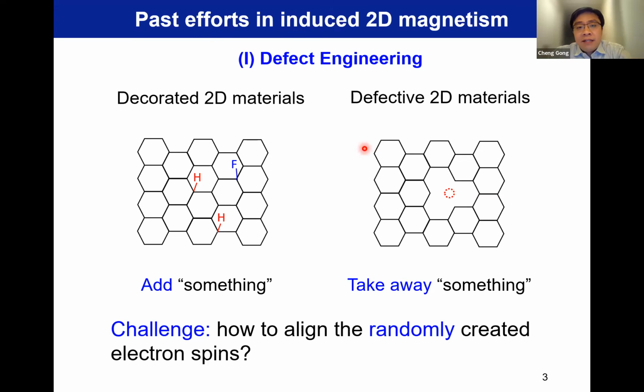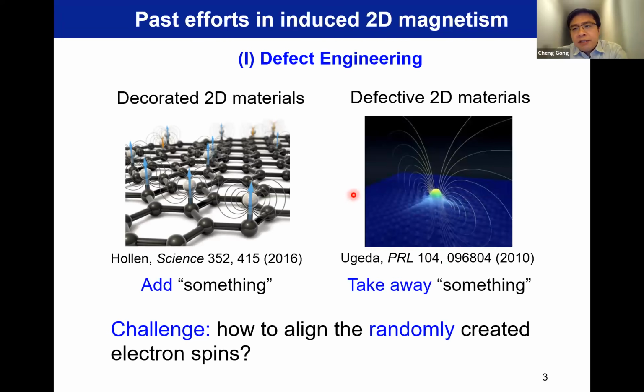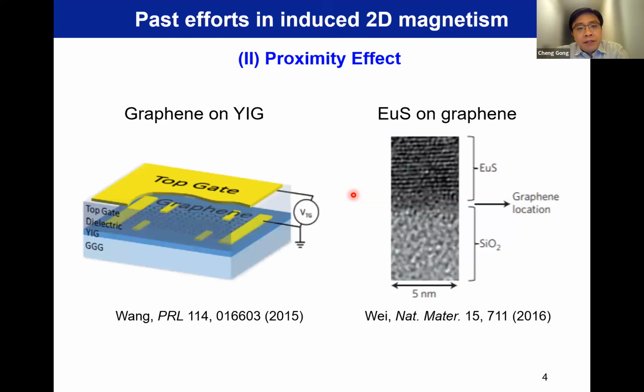No matter whether it's graphene, molybdenum sulfide, or such non-magnetic 2D materials, basically you can create a defect to easily introduce a local magnetic moment by either adding something or taking away some element from the lattice. So either way, you can create the local spin moment. But it's very hard to arrange these moments into a long-range magnetic order. Until even recently, I did not see a consensus in the field that this strategy has an unambiguous finding of magnetism.